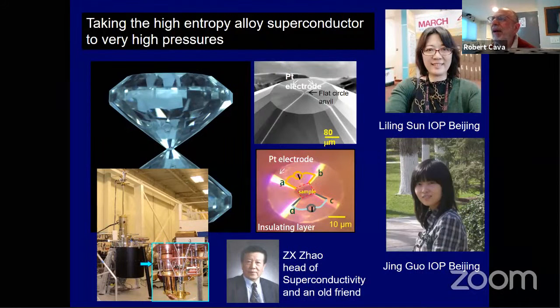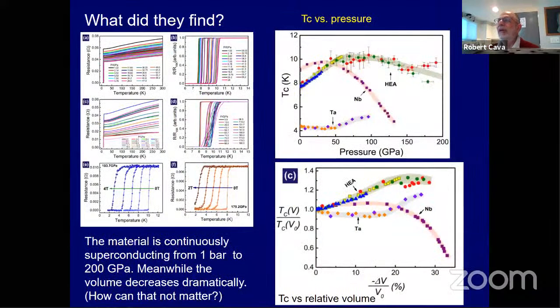And so they put some of my high entropy alloy superconductor between two diamonds, and they squeezed it. And what does it do? Well, first of all, if you're making these high entropy alloys, the reason that metallurgists were so interested in them in the first place is that their mechanical properties are remarkable. So I thought, well, maybe you could put these under pressure and they will survive high pressures. And if they can survive under high pressure, maybe they'll do something interesting. Maybe the superconducting ones will do something interesting under pressure.